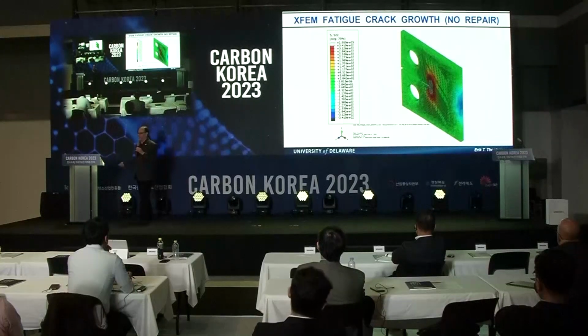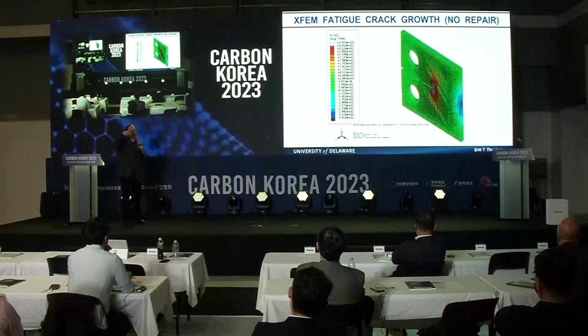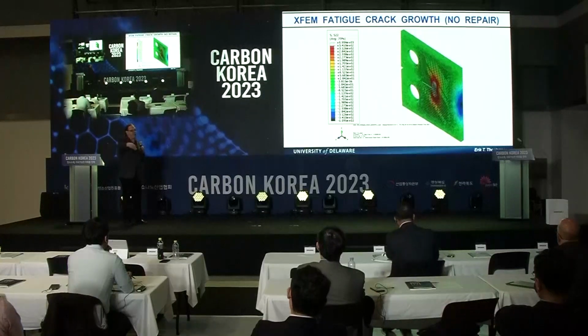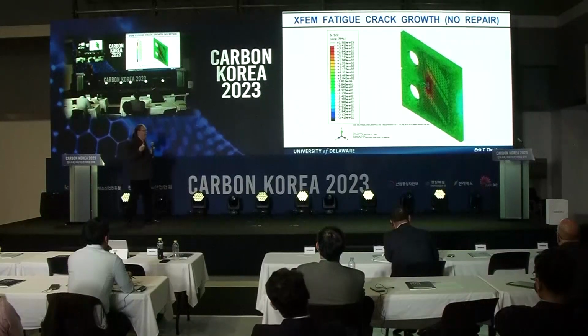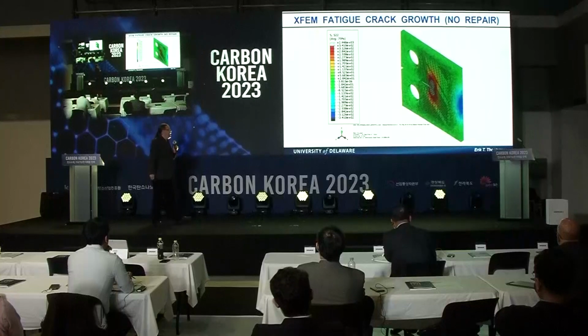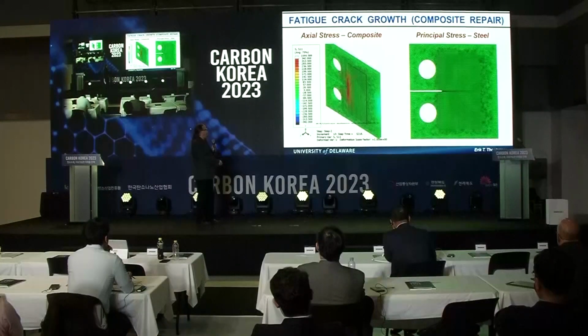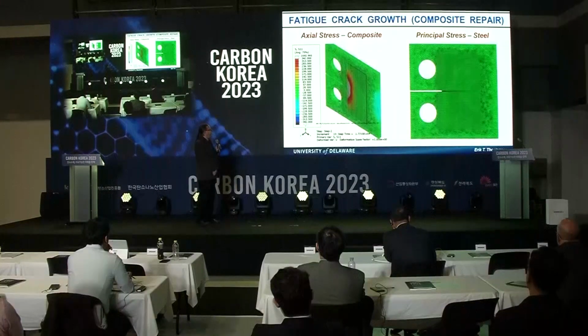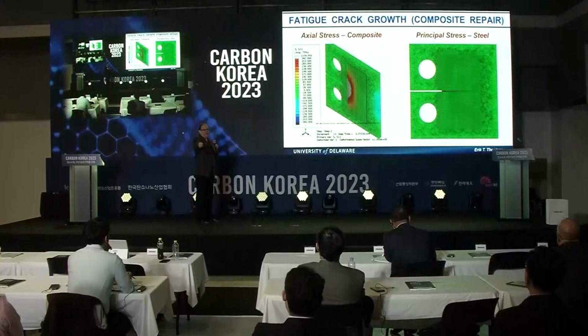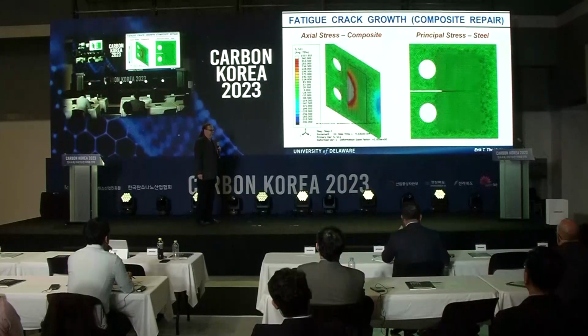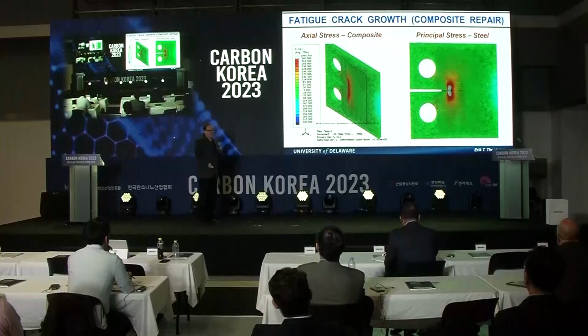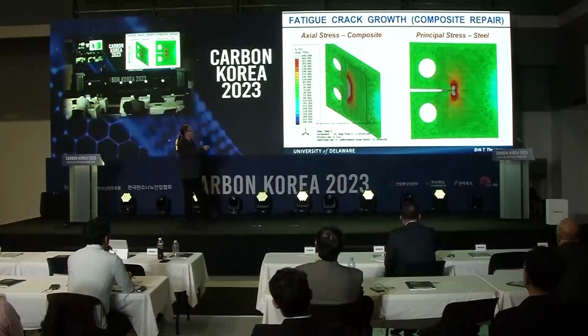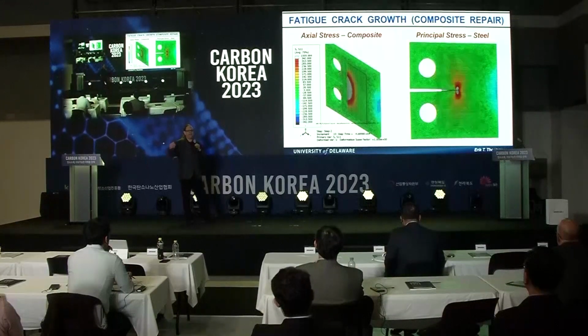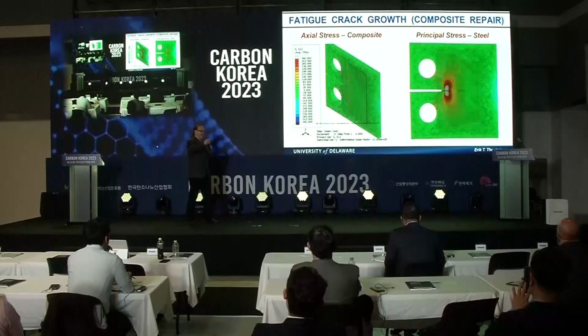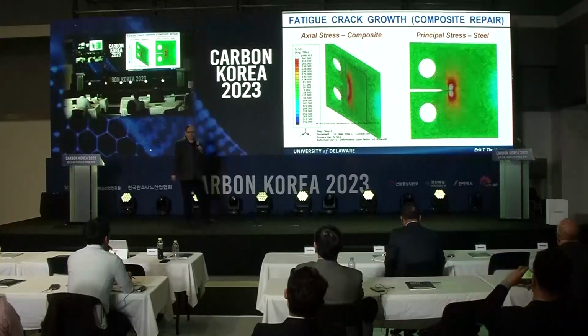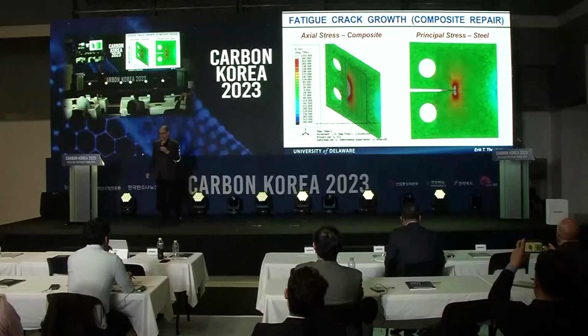So this is a simulation where that crack is growing, and what you see is that as the crack gets longer, the stress intensity at the crack tip increases. So this next slide, the first one shows this axial stress in the composite. Well, as that crack grows, the composite starts to carry load. But of course, you can't see it. And on the right-hand side, the interesting thing is that as that crack grows and the composite carries more load, that stress intensity decreases.